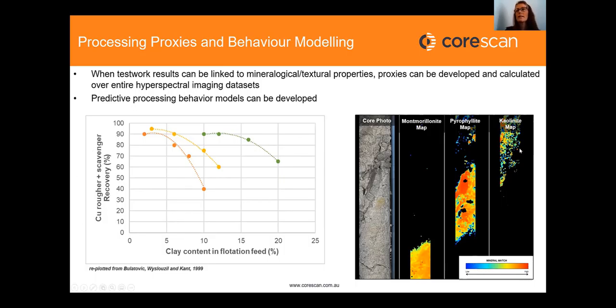And then we look at the image on the right-hand side of this slide, we can see that in the core photo, this is a fairly homogeneous piece of rock. But if you look at what it's actually made up of, we have a section of kaolinite in the top part of the image, we have a section of pyrophyllite, and then we end in a section of montmorillonite. So these would all probably be considered clay minerals in the processing, but the species of clay that are present actually have a really big impact on the processing. Montmorillonite is a smectite, it's a swelling clay. It's going to behave very differently than say the kaolin minerals, which do also affect the processing, but in a very different way. They're looking at increasing viscosity and different pulp and flotation behaviors. So again, it's really important that we have this data that's able to speciate the minerals that are there. But then again, this consistently collected data allows us to roll out the processing parameters that we observe on a small scale to a much larger data set.